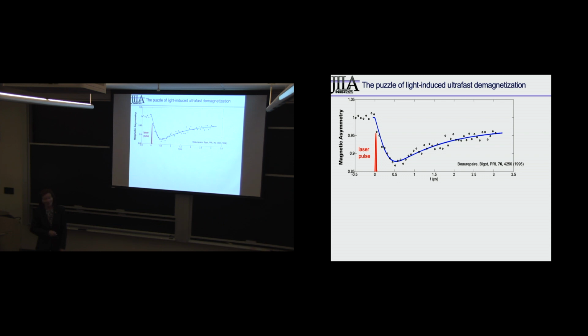So this was sort of the quandary, that you could make a really fast laser pulse. We can make 10 or 20 femtosecond laser pulses, no problem. But no matter what material one would look at, you'd get a curve for the magnetic quenching that looked kind of like this. It took about half a picosecond for the magnetism to quench, and then it started recovering. For those of us who do ultrafast science, this is a weird time scale, because it is far too slow to be associated with charge dynamics, which should happen in tens of femtoseconds, and it was far too fast to be associated with lattice dynamics, which should take about a picosecond to heat up. So this always looked a bit strange to folks, but that was what the data showed.